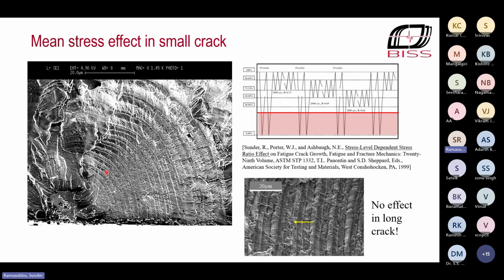And you can see that initially, as the crack grows, the crack extension in that step, the first step of 2000 cycles, is much more than the crack extension in this step. But as the crack grows larger and it becomes a long crack, the crack extension in all three is identical. So we drew the wrong conclusion that this is a small crack effect. And you'll find a lot of such papers in the literature called small crack effect. So it turns out if the crack is small, the effect will be there. When the crack gets large, it won't be there.